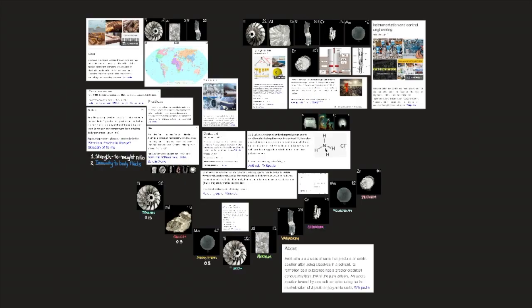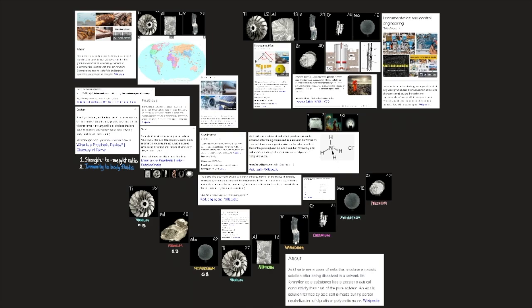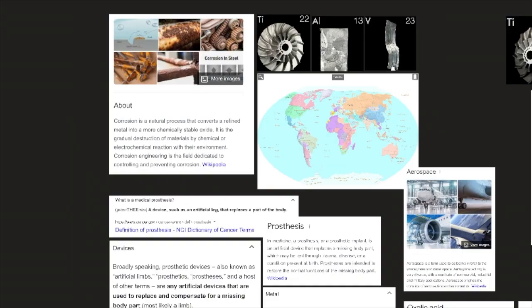When strength is not a major consideration, commercially pure titanium is the material of choice because of its low cost, ease of fabrication, and good corrosion resistance. Alloys such as Ti 0.15 palladium, titanium 0.3 molybdenum, 0.8 nickel, and titanium 3 aluminum, 8 vanadium, 6 chromium, 4 molybdenum, and 4 zirconium can extend the usefulness of the metal to either higher temperatures or stronger concentrations of reducing acids and acidic salts. In more recent years, more high-strength alloys have been utilized for corrosion applications.